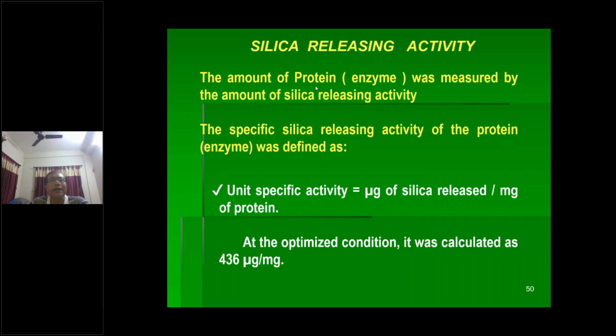Then the amount of protein was measured by the amount of silica-releasing activity. Basically, this is very important. That is what is called the specific activity: how many micrograms of silica is released per milligram of protein. Because we are isolating the protein, if we use 1 milligram of protein, how many micrograms of silica is released? That is the specific activity. In fact, at the optimum condition, it was calculated that 436 micrograms of silica was released per milligram of protein.